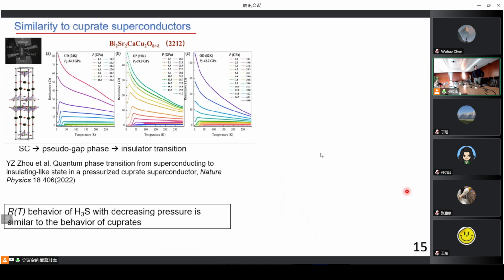In cuprates, a group from the Institute of Physics, Chinese Academy of Sciences, recently published a work in Nature Physics this year, 2022. They squeezed in a diamond cell a cuprate, which is one of the most two-dimensional cuprates known: bismuth strontium calcium copper oxide, 2212. And they found that after compression, they observed similar changes in the behavior of the resistance. Firstly, at low pressure, the behavior is metal-like in the normal state of this compound. But after compression, we see that Tc significantly decreases, and at the same time the first derivative of resistance changes its sign, and the compound goes to the semiconducting state. So it's a transition between the superconducting pseudogap phase and the next, insulating phase in these cuprates.